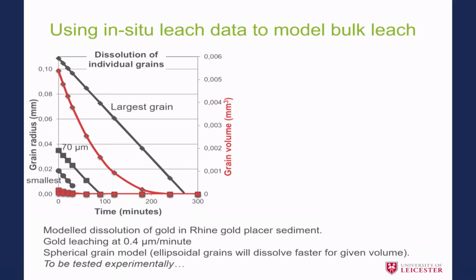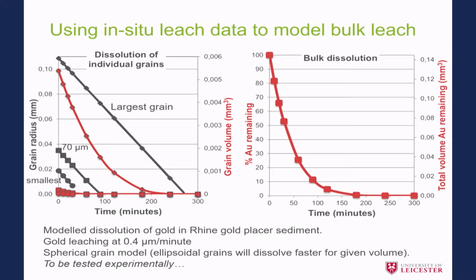We can do that for individual grains and then add them all up in a spreadsheet, and we come out with what we think is going to be the bulk leaching behavior of the whole sample. Okay, this is our prediction, and we can see that in an hour we've got about 75% out, in 2 hours we've got 95%, and then in 3 hours we've got 99.5% of the gold out. This is our prediction. We're now working to do the bulk leaching experiments to test this.